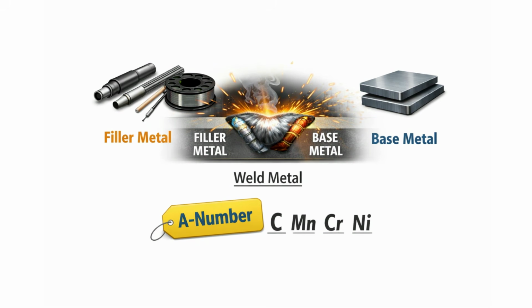The A number relates to the chemical composition of the weld metal, the combination of base metal and filler metal after welding. These codes help identify the weld metal chemistry in the procedure qualification record, PQR, and WPS. ASME Table QW-442 assigns these A numbers based on alloy percentages in the deposited weld metal. If a weld metal composition doesn't match an A number, the exact chemistry must be recorded.